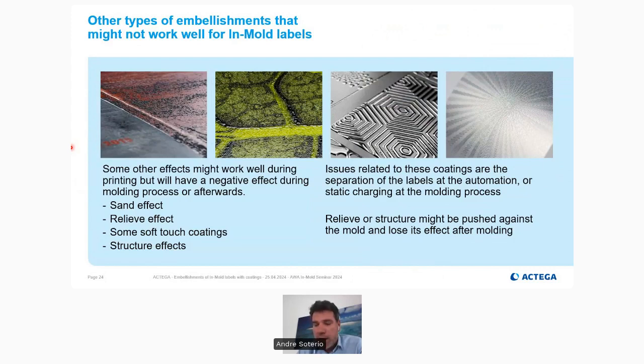And the main reason it's not working is that there will be a lot of issues related to the separation of the labels, or when you are trying to place the labels inside the mold with static. And with some of this relief structure, after you inject and press the label against the wall and the plastic, it will become quite flat and you're going to lose the desired effect.